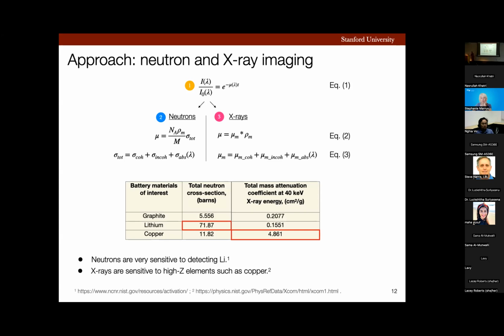Now, if you look at the X-ray side, you can see that mu is directly proportional to mu m, which is the mass attenuation coefficient. Like neutrons, it's a summation of coherent and incoherent scattering, and absorption. And if we look at the right side of the table, you can see that its value for copper is pretty high, which means X-rays are sensitive to high Z materials such as copper. Thus, we can use the sensitivity of neutrons to lithium and X-rays to high Z materials such as copper to detect lithium on graphite in situ in a full cell battery.